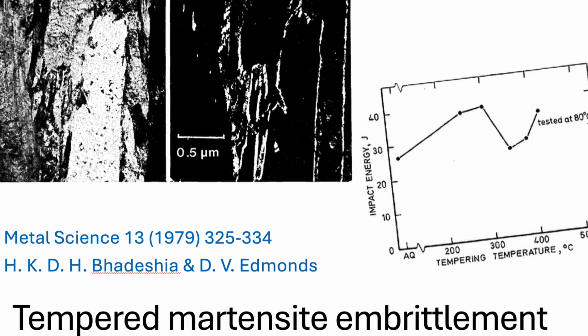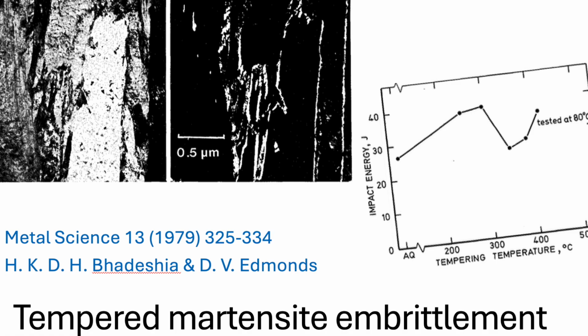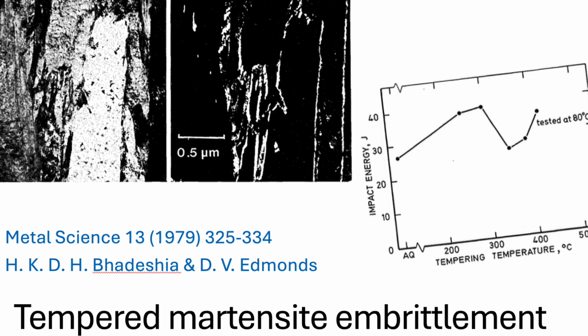See them directly. So we already established these thin RA films are prone to transforming, right? And that transformation itself creates stress, imposes constraints on the surrounding martensite laths. Okay. The theory was that the products of that RA transformation, what it turns into, are the true culprits behind the embrittlement. And what did the TEM show? What was that specific transformation product? It showed intralath cementite precipitation.